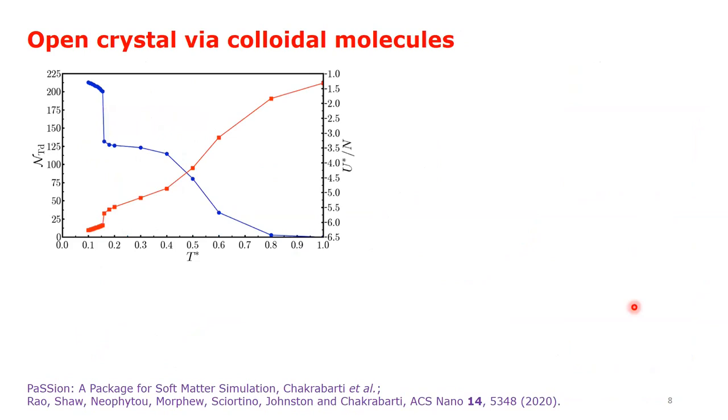A series of Monte Carlo simulations with 500 particles under periodic boundary conditions show that a tetrastack crystal can indeed be self-assembled from our designer tri-block patchy particles.